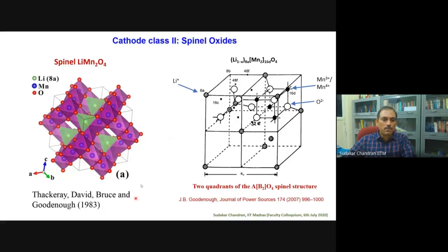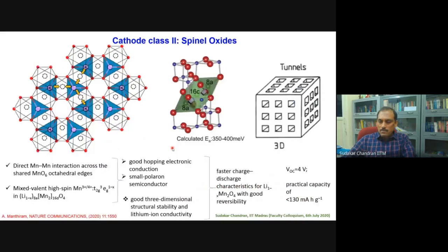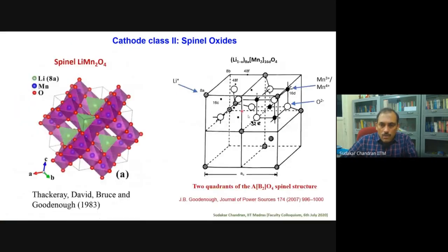So he came to Professor Goodenough's group, and then with Goodenough together, they came up with a second material. That's a second wonderful material, LiMn2O4. It's a spinel composition. The lithium sits in the A sites. That is the 8A position, the Wyckoff positions. And then the manganese sits at the 16d position. And oxygen forms a close packing again, cubic close packing. So in this particular compound, the lithium diffuses from tetrahedral site to another tetrahedral site through the 16C sites here.